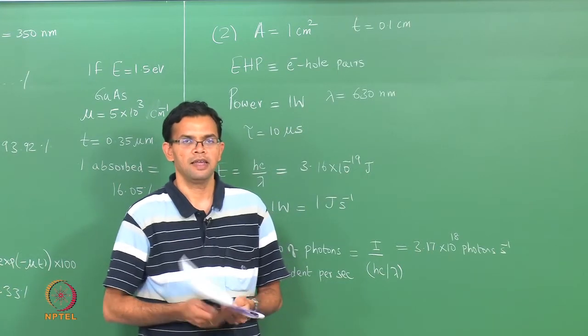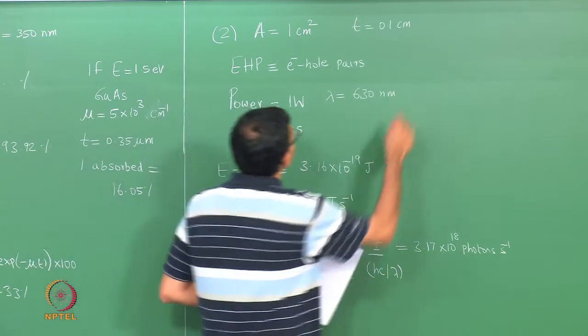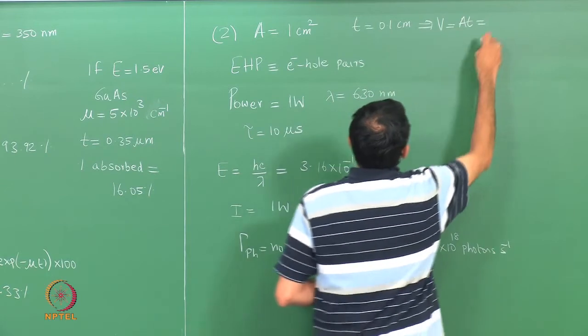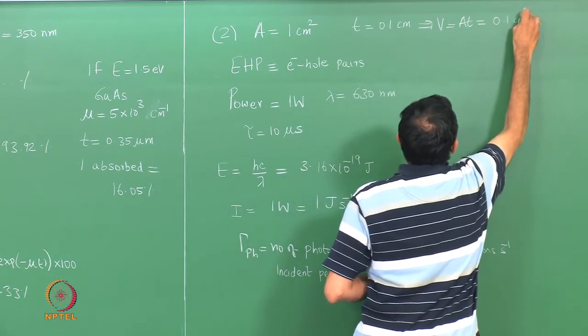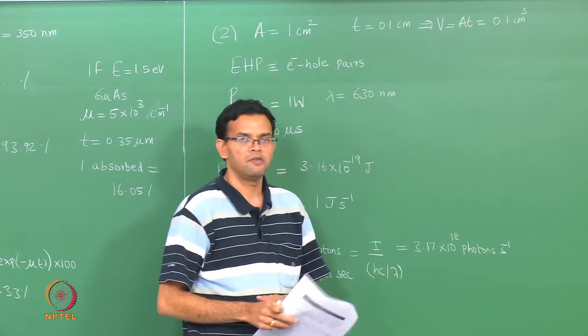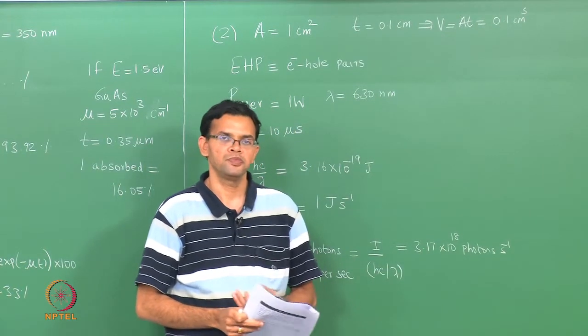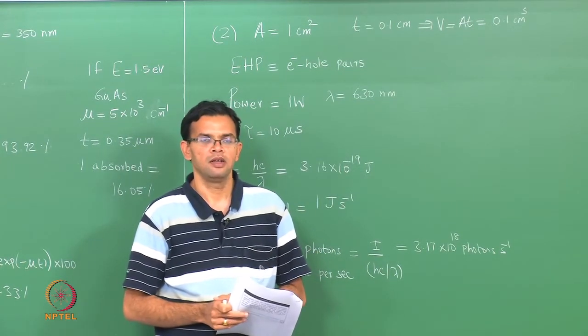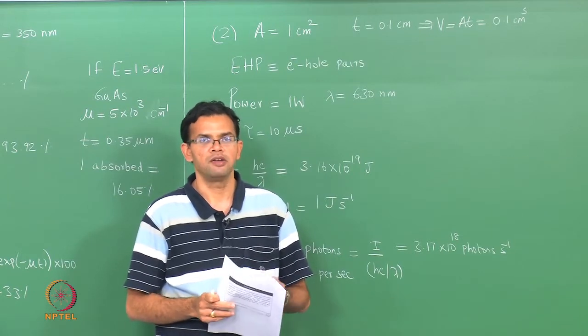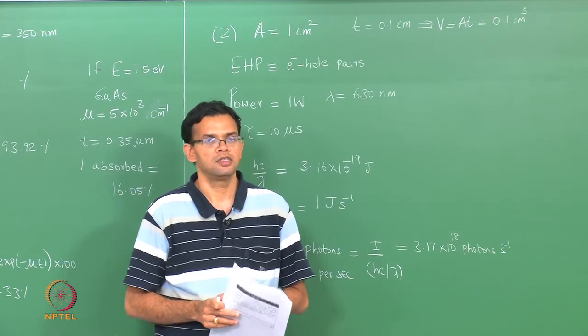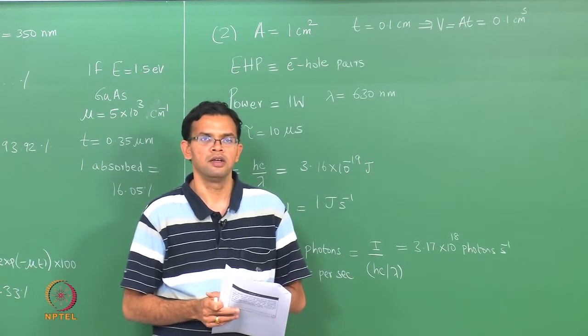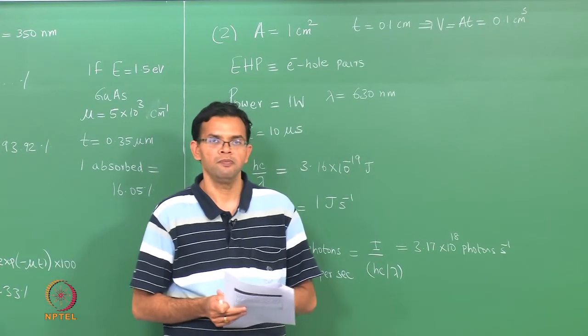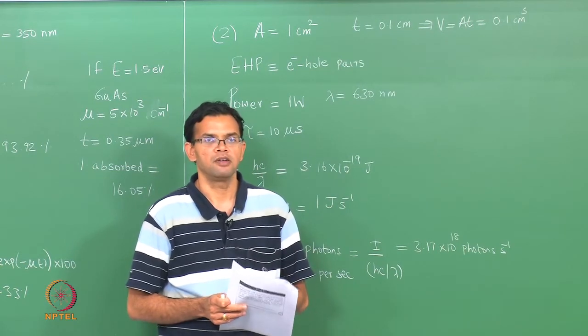Plugging in the numbers, we get 3.17×10¹⁸ photons per second. We also want the electron-hole pairs per unit volume. The volume is A × t = 0.1 cm³. We say each photon gives rise to one electron-hole pair, meaning a quantum efficiency of 100%. Usually that is not the case — quantum efficiency would be lower and you would multiply by the appropriate fraction — but for this problem we take it to be 100%.